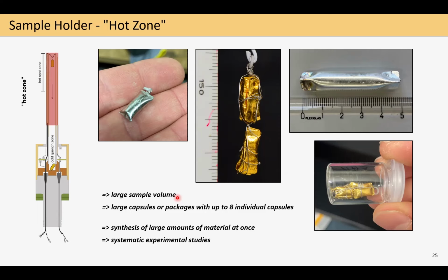And secondly, due to this large volume, this allows us also to run quite some systematic experimental studies. So imagine, for example, that you want to have a look at the effect of water on phase equilibria. So you can take one bulk starting material composition and prepare capsules with up to 8 different water contents, which you then can, as such a package, run in only one experimental run at the same temperature and pressure, and with just running the IHPV once, you can already create quite an extensive data set. So if you want to do systematic studies, I think IHPVs are also very, very useful tools.